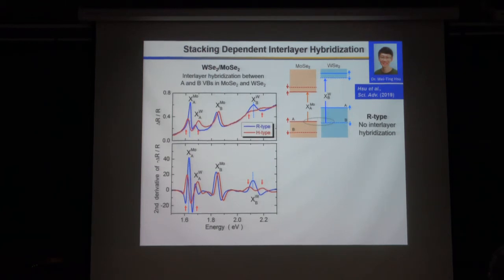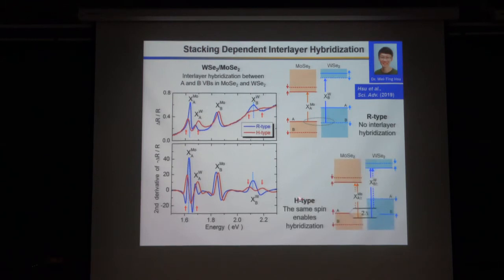So if you have so-called R-type stacking, actually these two bands will not hybridize. But if you change to H-type, the two bands become the same spin. So they see each other and they become hybridized. So they will form bonding and anti-bonding states. That's why we can see some splitting here, which corresponds to the hybridization strength of this band.